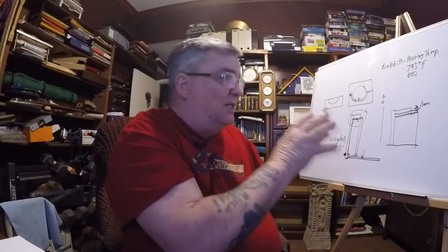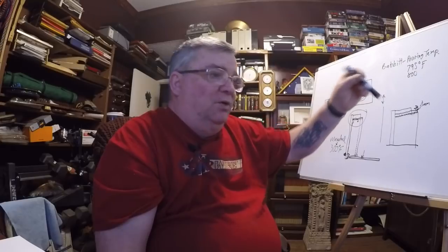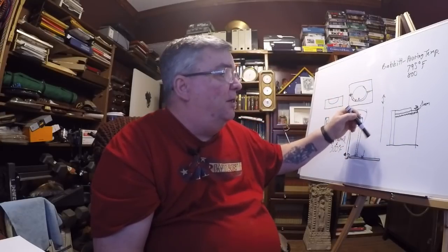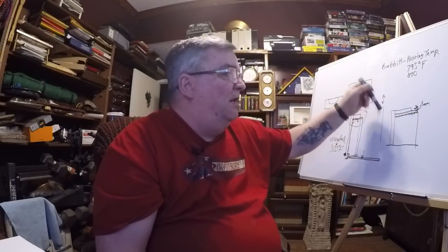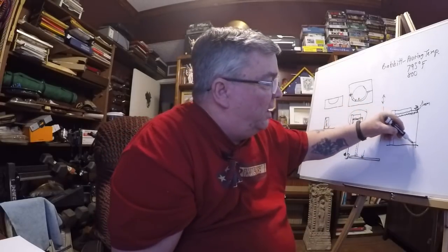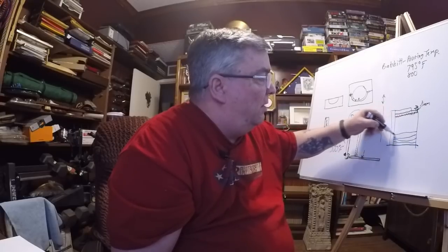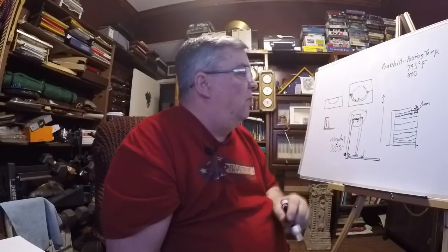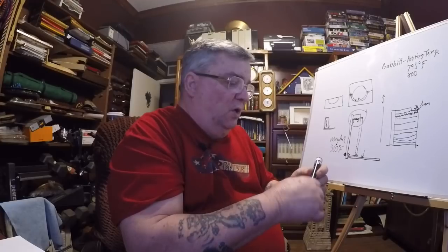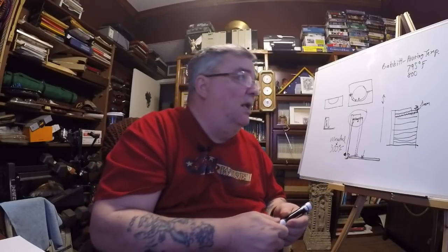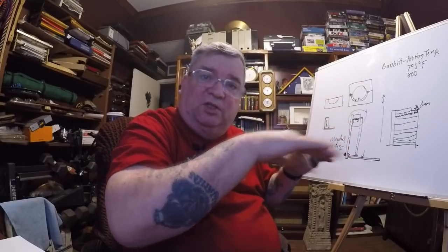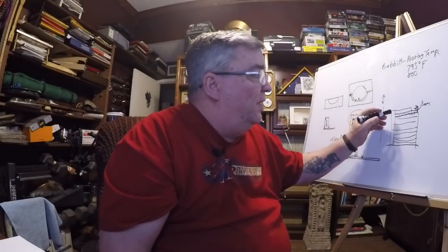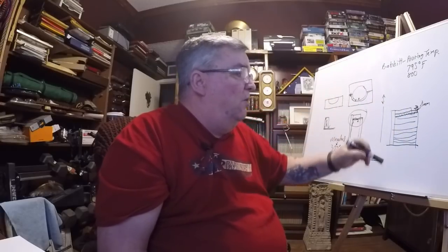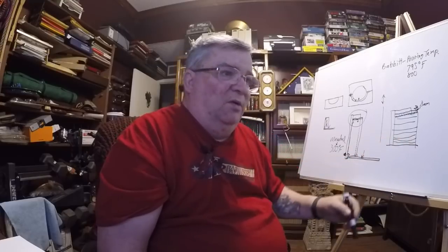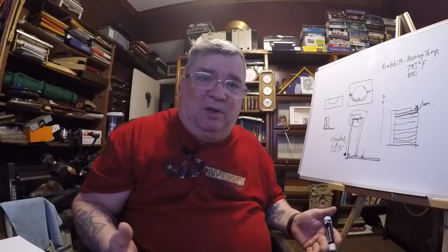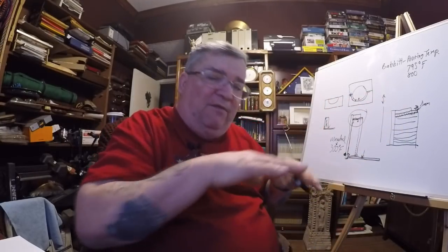You have a massive Babbitt in there that's now got to cool. Somebody is going to be using a churning rod and churn all the way around everywhere from side to side, and you're going to follow this material as it solidifies from bottom to top. You continue to do it until it's solid all the way up to there. Once it's solid all the way up, you take a torch, or it could be a heat gun, for that matter, and you hit it and let it flow until it's smooth, because it's not going to be smooth when you're done. Even when it's almost all the way up to the top, you're still going to be hitting it, so it's going to be like a moonscape. It's not going to be smooth anymore. So just to dress it up and make it look good, you take a torch, heat it up and let it flow nice and smooth.